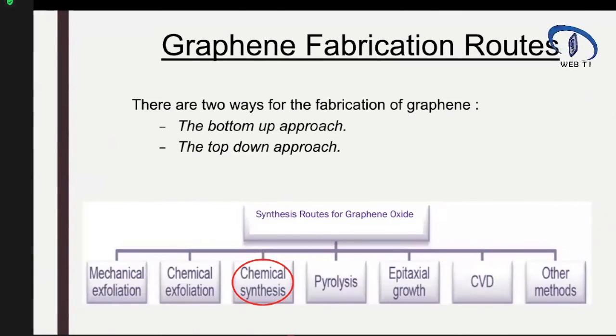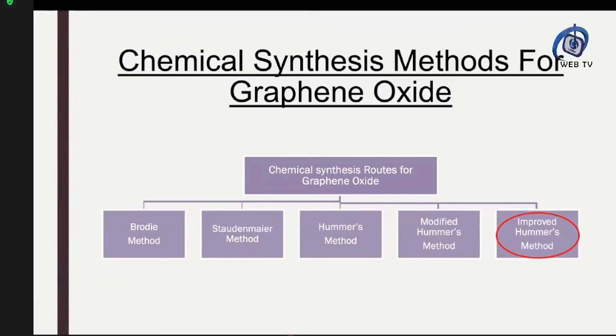What are the different fabrication routes which are used extensively for graphene fabrication? Mechanical exfoliation was the route which led to the first experimental extraction of graphene. Then chemical exfoliation, chemical synthesis, and epitaxial growth, CVD, are different famous routes used for graphene fabrication. Here we will be talking about graphene oxide, which can be very well extracted from the chemical route. The chemical synthesis routes for graphene oxide are more than one, but the one easily used at lab scale